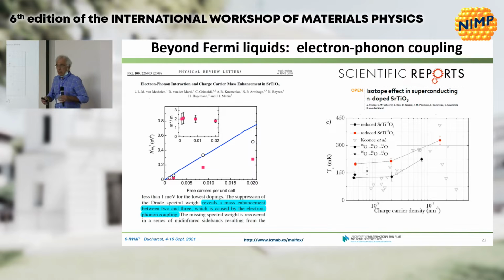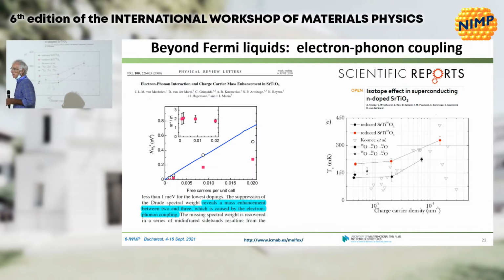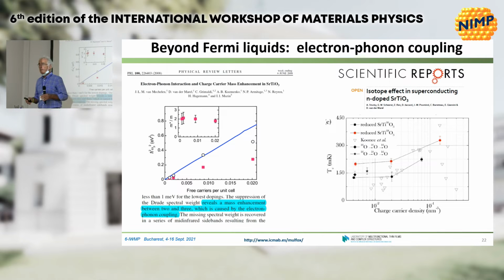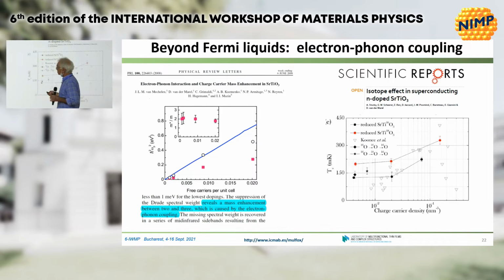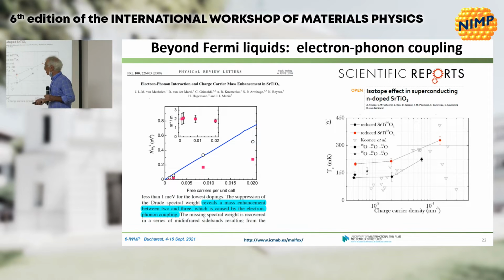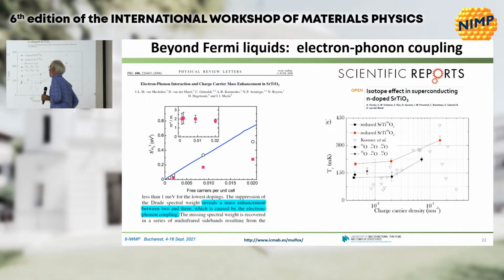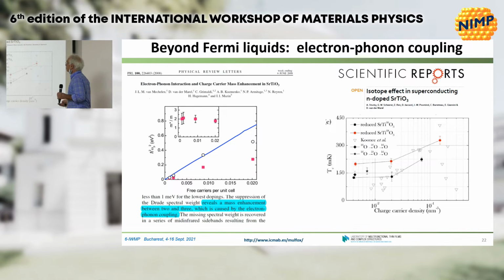First, in oxides, and in particular in perovskites, there are many fingerprints that electron-phonon coupling could be very important. Not in those metals, but in other materials, some people did in the past some experiments. Here I'm plotting some data, PRL 2008. This is the plasma frequency obtained in strontium titanate, measured as a function of the carrier density. It's obvious that the data should go along these open points here, but in fact they go here. So the mass is larger than would be expected if the electrons were almost free. So the mass depends on how many electrons you have. That shows that there is some indication of electron-phonon coupling.